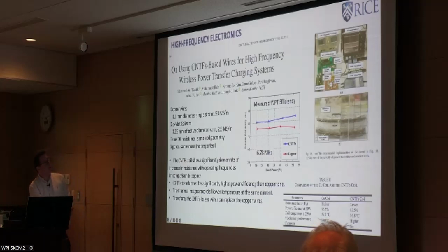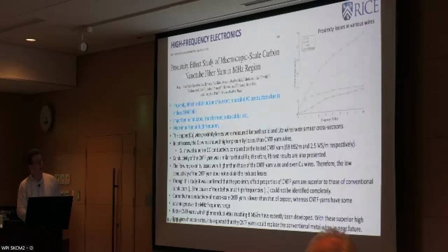This is the group of Jong Park in South Korea, and what they saw is, again, even though the copper wires had higher conductivity than the carbon nanotube fibers, when they got to higher resistance, the fibers had better behavior in transformer efficiencies. And part of it seemed to be also due to the thermal conductivity, which is very high.